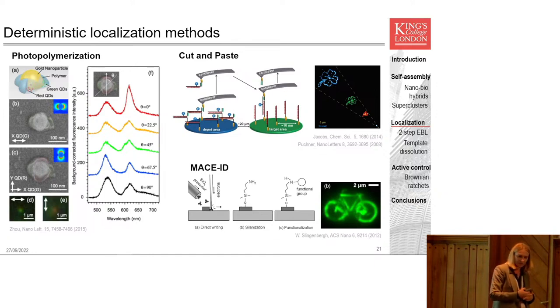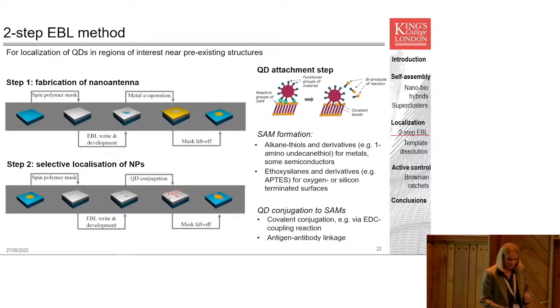When choosing a technique, you always have to think about what it is you're trying to achieve and what the limitations of each technique are. So to give you an example, in our research, we were very interested in using this two-step EBL method, which is a method for localization of nanomaterials, or quantum dots in this case, in regions of interest near pre-existing structures. As the name suggests, it involves two steps of EBL writing, where the first step involves the fabrication of nanoantennas. And then in the second step, you repeat the EBL and you align your write to the first layer. But in this write, instead of depositing metal, you perform a chemical reaction to attach your quantum dots to the substrate in the exposed holes.